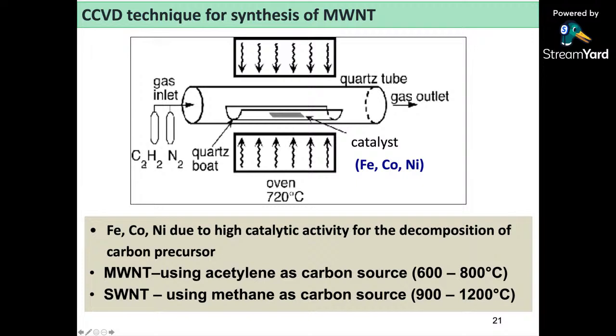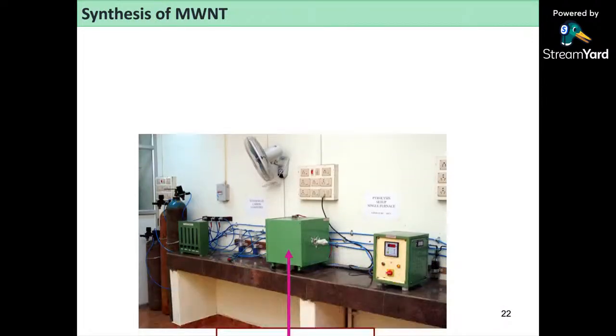We use acetylene as a hydrocarbon at a furnace temperature of around 700 degrees centigrade. What happens is that this catalyst will decompose this hydrocarbon into hydrogen, which will go out, and carbon will get dissolved in the iron, cobalt, or nickel, and then from getting saturated and then supersaturated, one can get these carbon nanotubes. Very simple technique, the chemical vapor deposition technique, most of them use.